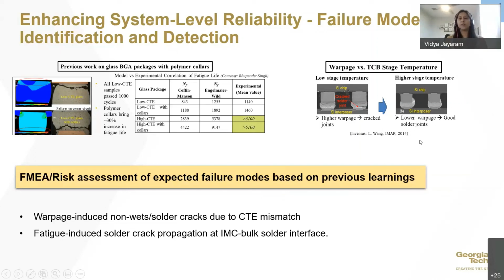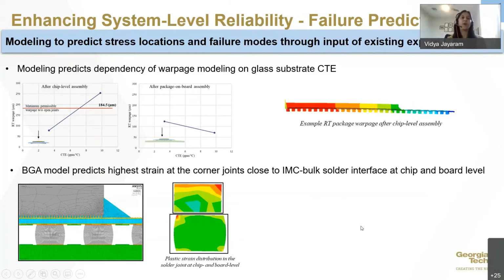And the other one was warpage related or warpage induced defect, where we saw that it was critical to optimize your process conditions to get the warpage as minimum as possible during processing, so that you don't induce additional failure modes. So here the warpage was dependent on the thermal compression bonding at the chip level, by changing the temperature profile that was used. So these were the two key failure modes that were identified. And then we developed a model around it to predict what kind of failures we might see, and if that's similar to the learnings that we've had in the past.